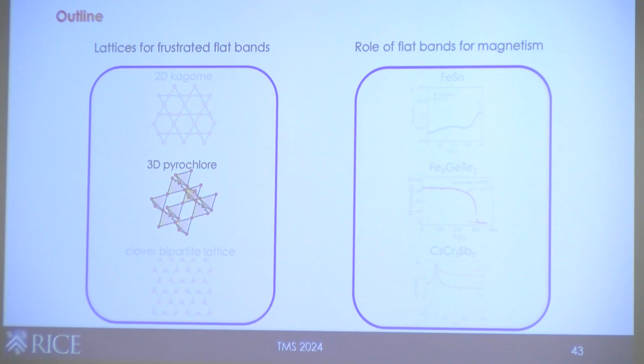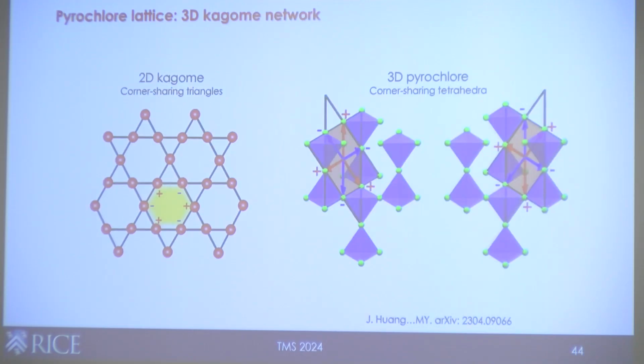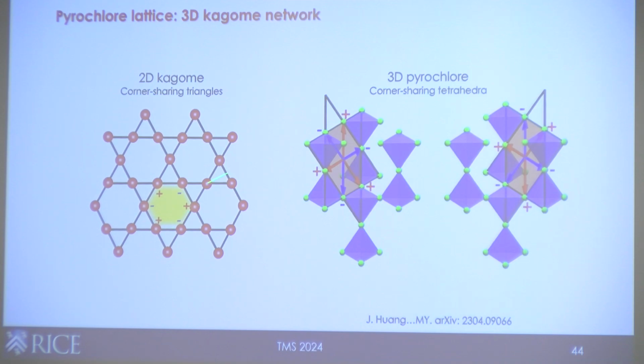Okay, so pyrochlore. As we have learned from the candidates for quantum spin liquids, we know that one way to go from 2D to 3D is to go from Kagome to pyrochlore. Essentially, Kagome is made of these corner-sharing triangles. Pyrochlores are made of corner-sharing tetrahedra like this. And there are ways you can cut through a pyrochlore lattice that would expose these Kagome planes. So if you cut along the 111 direction, you can trace out this is the Kagome. This would look like a Kagome layer. And there are 3 ways to cut this. So this shows you 2 of them.